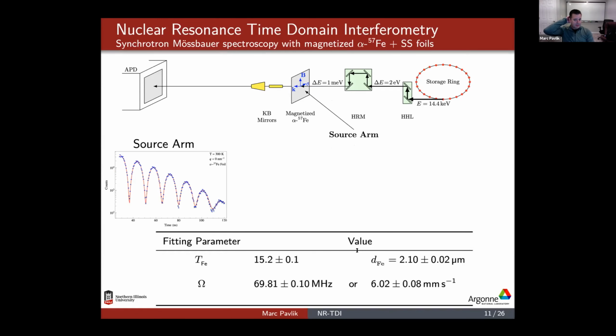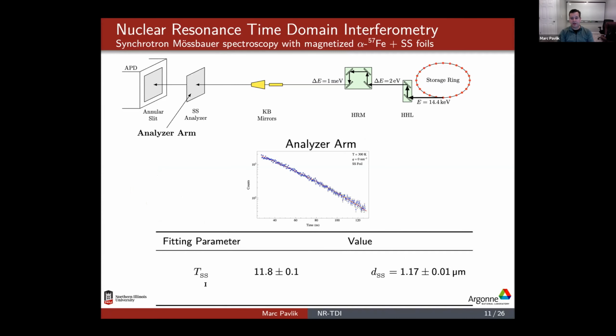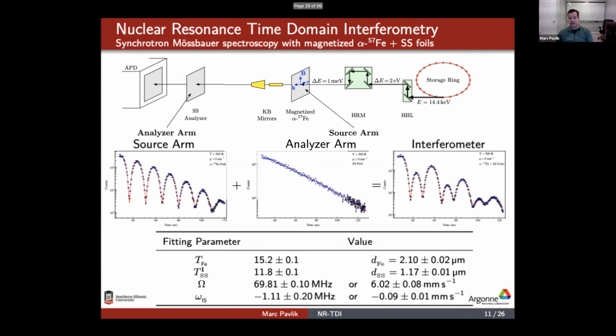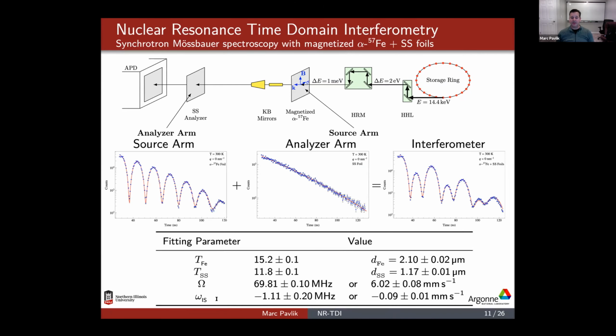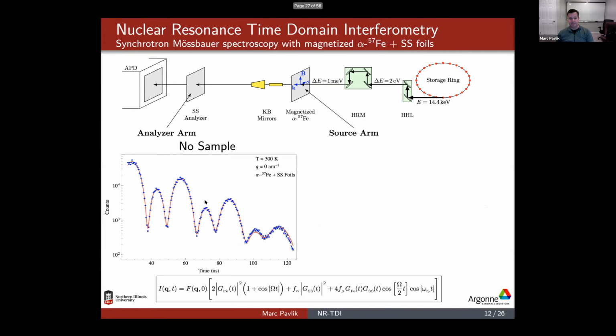The way we set this up is we have to set up calibration foils. We start with the stainless steel and the magnetized alpha iron foil, which allows me to determine the fitting parameter for the effective thickness and what my beat frequency is. Next, in the forward direction, again just the iron foil itself, I can measure the effective thickness. If I add these two together, it creates my interferometer. It also allows me to figure out the isomer shift. But I have this reference beating spectrum here, and this is the equation we use to fit this beating pattern.